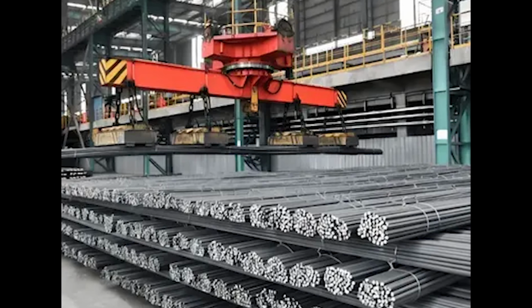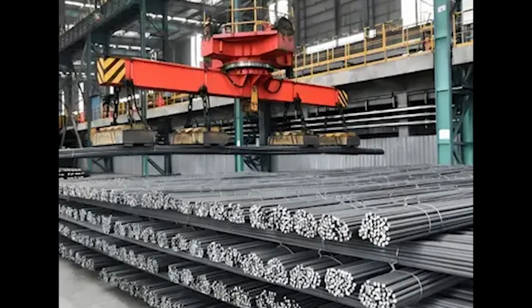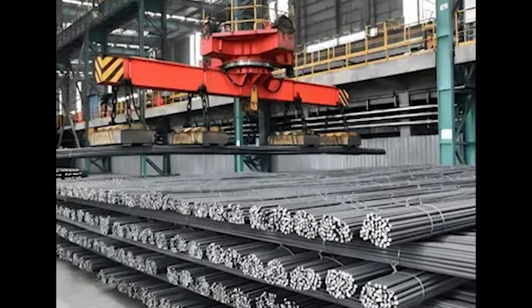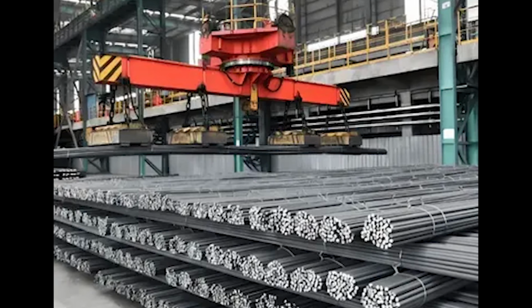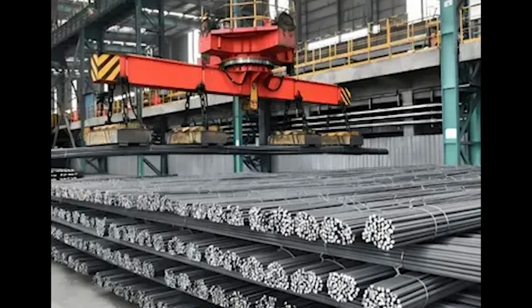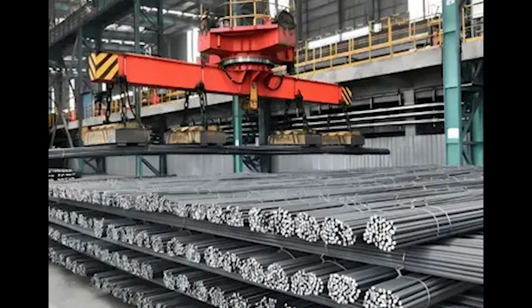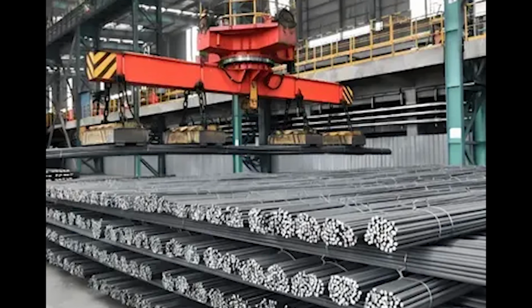Most critically, those finished bars would air-cool on the run-out bed for 45 minutes, allowing their microstructure to transform naturally into fine pearlite and ferrite, rather than the brittle martensite that resulted from rapid quenching.